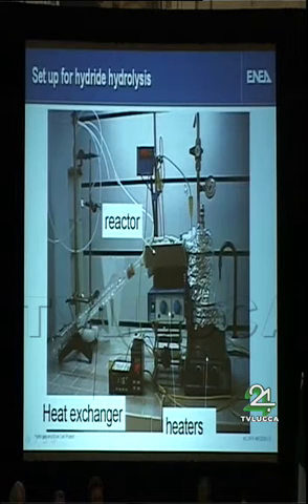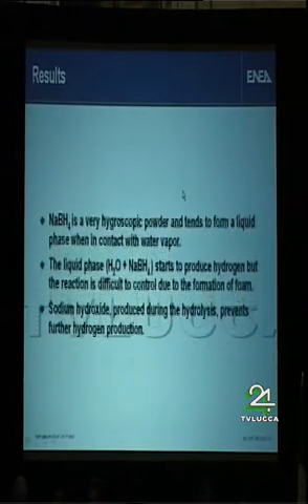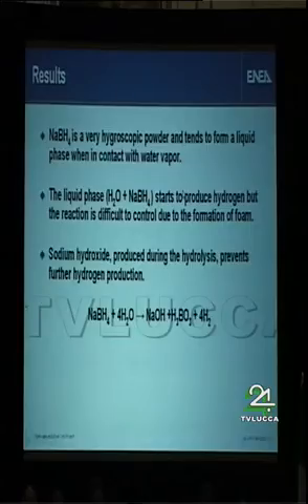With this, the result of the experiment is that sodium borohydride is a very hygroscopic material, and when the water pressure is very high in the vapor phase, part of the water passes from the vapor to the solid phase and is absorbed on sodium borohydride and forms a liquid phase. The liquid phase, formed by a solution of water and sodium borohydride, starts to produce hydrogen, but the reaction is difficult to control due to the formation of foam that brings the solution outside the reactor.